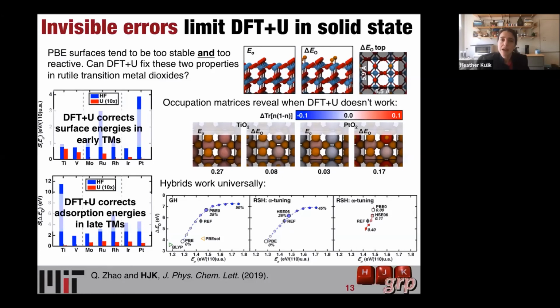However, what I would say is that knowledge of sensitivity of the property you want to predict to Hubbard U should guide you, because for sure, even compared to a hybrid functional, computing your result at Hubbard U of say 5 eV, 4 eV, and 6 eV, that should all be linearly varying, and you can reconverge your electronic structure at these different Hubbard U values, just changing them slightly, and that will give you a good central difference approximation to how much Hubbard U is going to change the property you want to predict. That's probably ultimately what I'd advocate, especially if you're just aiming to get a range of properties correct and try to know how much the U is influencing that property prediction.